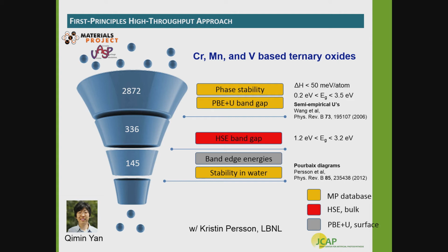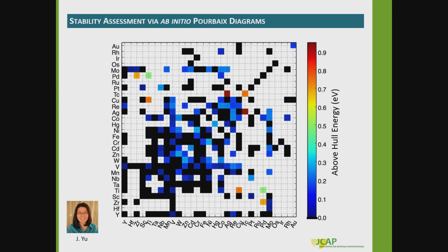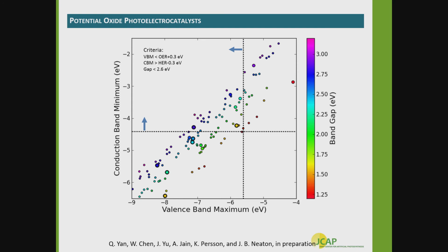A third stage focused on understanding and computing the band edges and understanding the stability in water, including some very interesting work on computational mapping of Pourbaix diagrams to understand the electrochemical stability. And then finally, generation of some selected candidates. So this stability assessment with the Pourbaix diagrams yields a large number of potential candidates from which we can now select materials that have proper alignment of the conduction and valence band energies. And among these, two candidates stood out, which were manganese nickel oxide and manganese vanadium oxide, manganese vanadate.